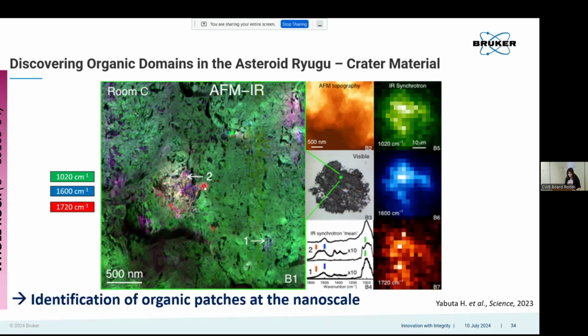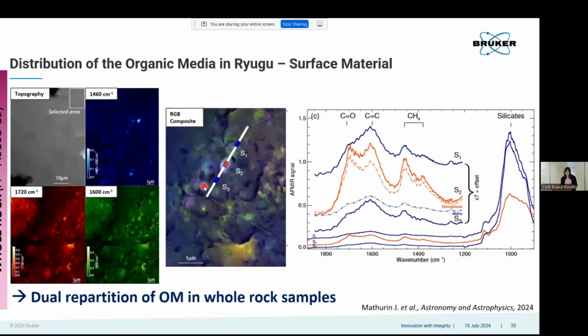There you go. But also, similar to that ZAG meteorite sample, in the Ryugu surface sample, so this is the A sample, which doesn't come from the crater, what you see is a similar story of organic material within the sample. In some areas, again, you have more of these carbonates, in some areas you have more of these PAHs, but you also have carbon-hydrogen bonds that are starting to be revealed. And they're not necessarily related with each other.